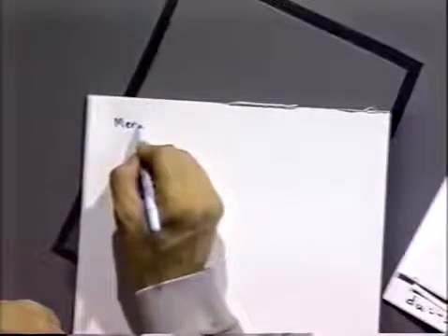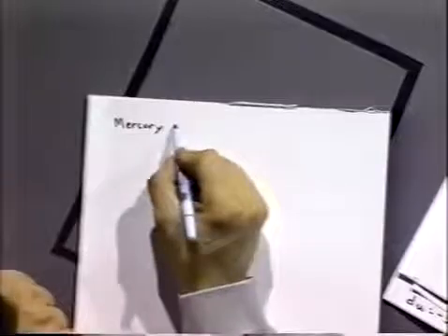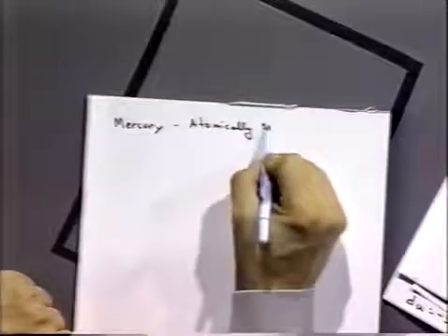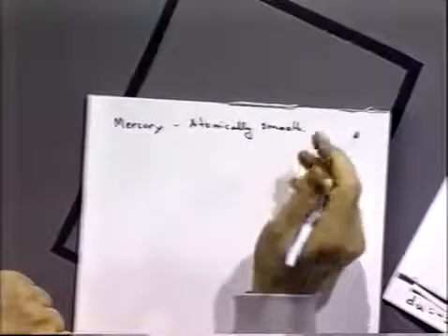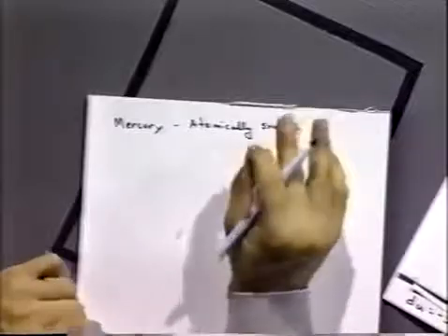A couple of solutions. One is to use mercury. Mercury electrodes are useful for a lot of reasons. One of them, though, is that they are atomically smooth. Although they can have ripples on them, they can have standing vibrations on the surface that effectively cause it to be a little bit larger than you can see. But platinum electrodes or carbon electrodes or gold electrodes all will have some deviation from unity between the geometrical and true area. Also, our yardstick changes as we change the time scales.